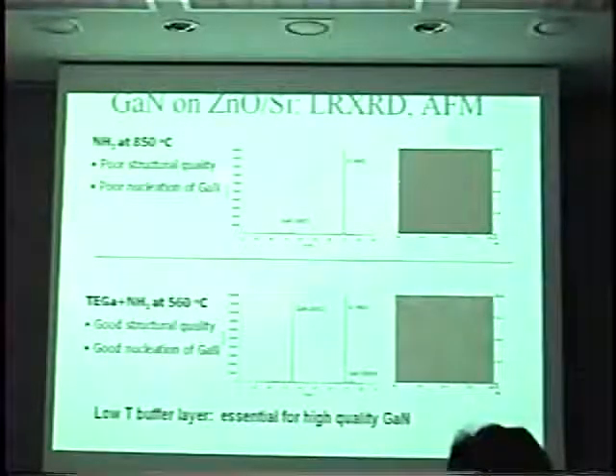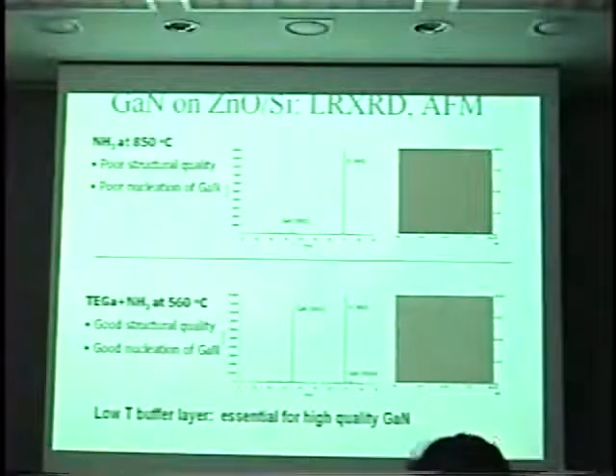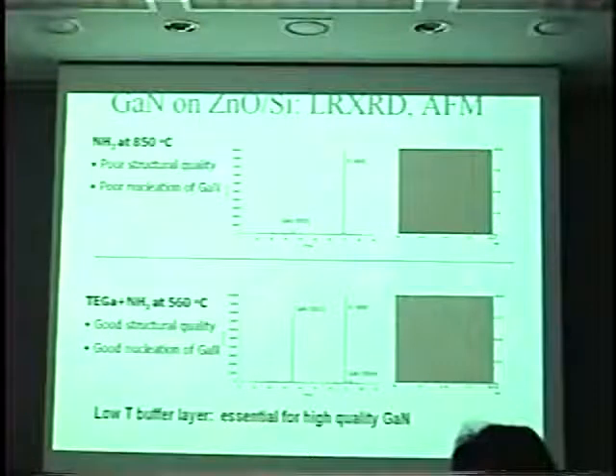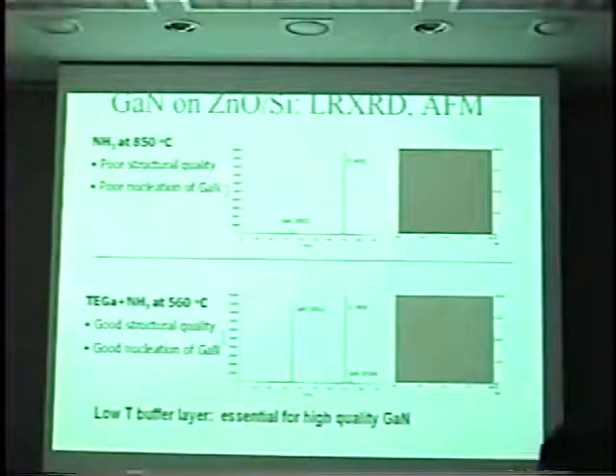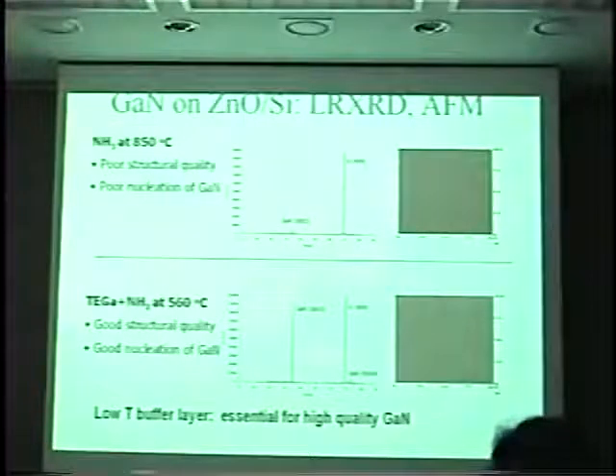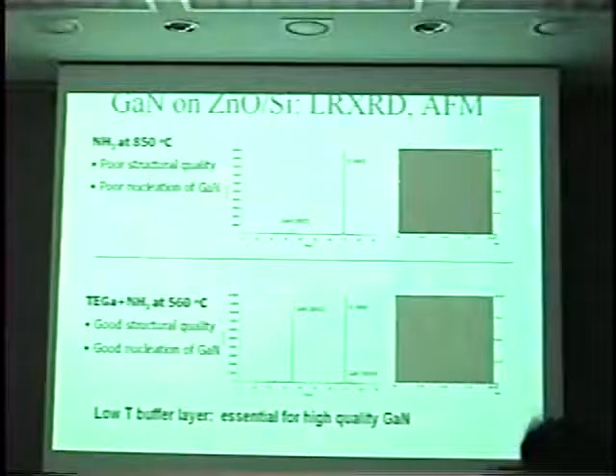Here is just a low resolution XRD scan of gallium nitride grown at the higher temperature. We get very poor signal relative to the underlying silicon for the gallium nitride. However, doing the low temperature buffer layer growth of gallium nitride on the zinc oxide produced a smoother surface morphology as well as a much higher quality gallium nitride. The zinc oxide was put down by pulsed laser deposition. Interestingly, it grew c-oriented regardless of whether we were using 111 or 100 silicon. Very surprising. The quality of the gallium nitride grown on the zinc oxide, however, is not as good as that grown on aluminum nitride, or even that grown directly using the in situ oxynitride interface.